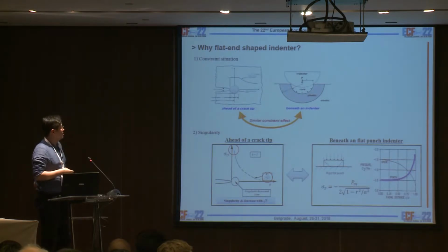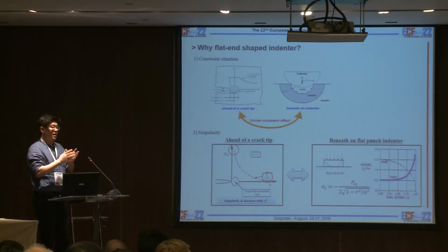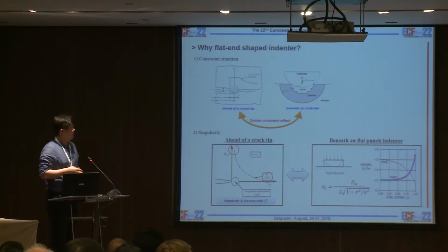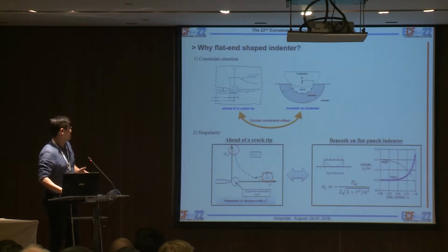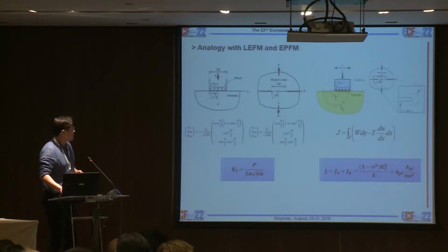The first one is the constraint situation. We know a plastic zone occurs, surrounded by elastic parts, ahead of the crack tip. And the same as in the indentation test, a plastic zone occurs during the indentation, surrounded by elastic zones. Also, if we use the flat end shaped indenter, we can observe a similar singularity at the edge of the indenter. So from these similar points, we thought that we can find a similar mechanics state between the two tests.